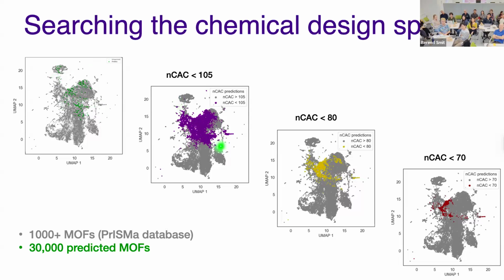Here are the materials where our model predicts it's less than 105. And you see here a region where there are only 4 materials, and we didn't even sample them, and those materials are non-porous. So what you see here is that if you make the net carbon avoidance cost smaller, you start to zoom in on particular regions of the design space. You have materials that are very good here, and materials that are very good in here, but they're still far apart. So apparently, for different chemical reasons, you have a good material. And if the underlying descriptors of these UMAPs were more interpretable, you could go back and inspect what characteristics make a good material.